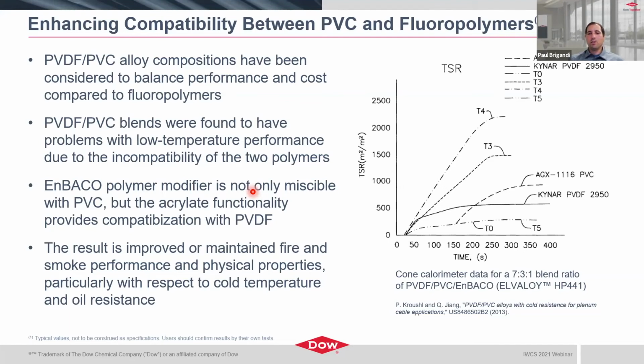What has been demonstrated by this group here is that when you incorporate, in this case, the butyl acrylate polymer modifier, you're able to provide miscibility, not only with the PVC, but now the acrylate functionality provides some compatibilization with the PVDF. And so that's going to result in improved mechanical properties with respect to cold temperature and some fluid resistance.